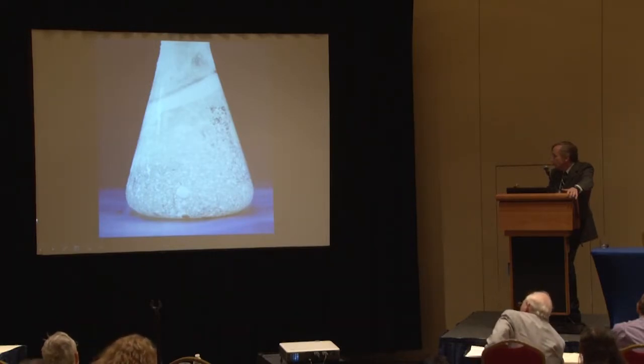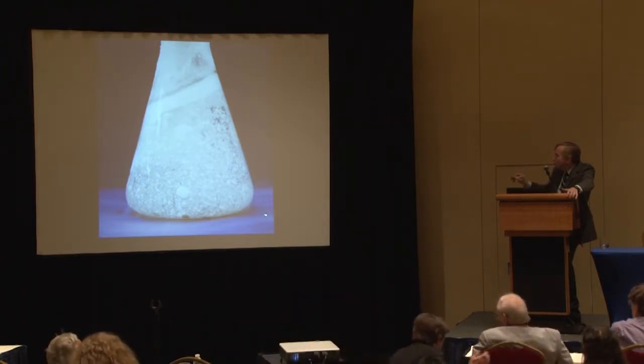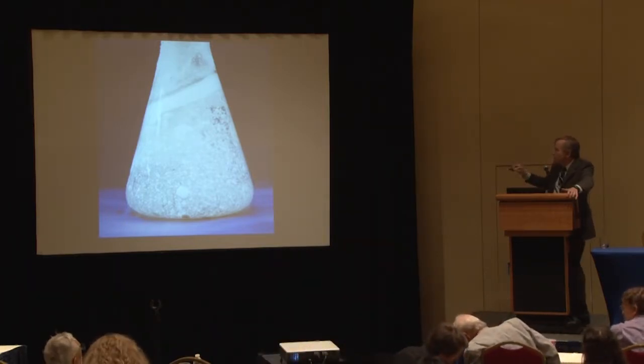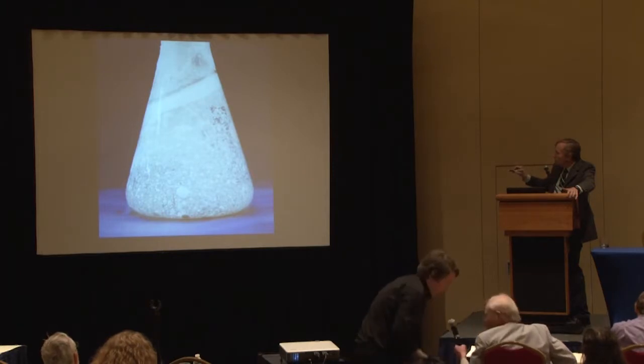In the laboratory, heterogeneous nucleation looks like this. This is a substantial concentration of ethylene glycol that we've vitrified, or I should say attempted to vitrify. And you can see in the solution that there's a large number of ice balls in it. At the center of each ice ball is a location where heterogeneous nucleation occurred, and then ice grew around that nucleation center as cooling continued.